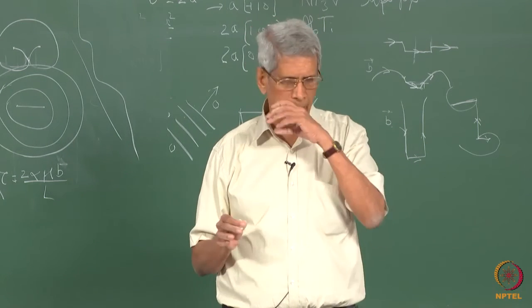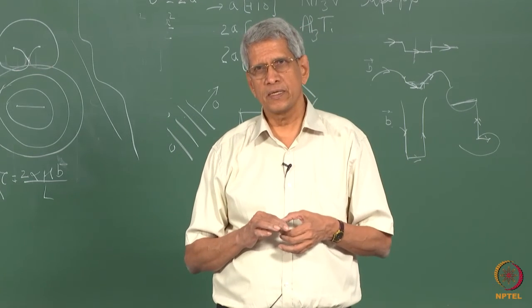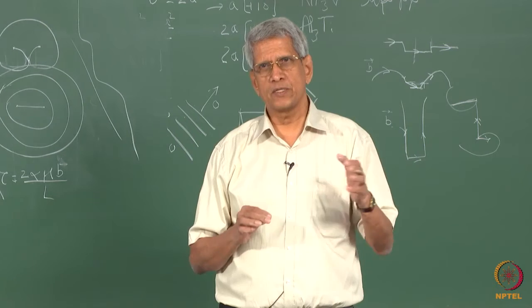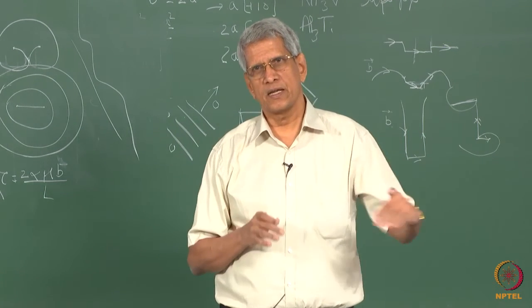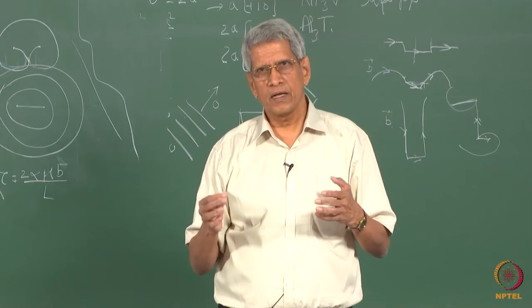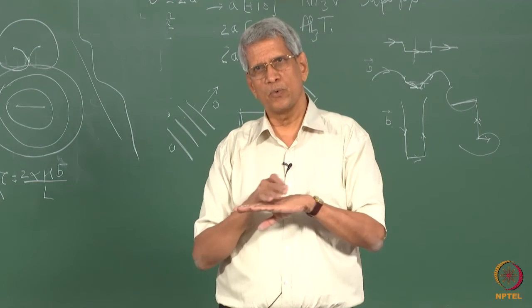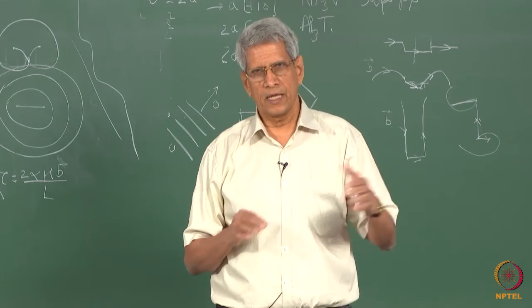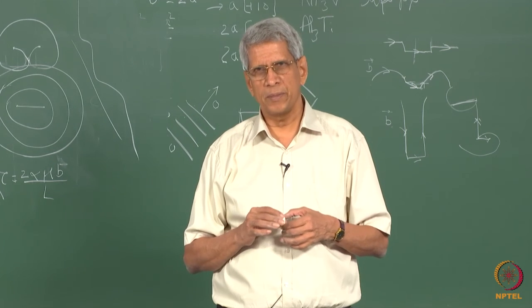When the applied stress is low and only one slip system is activated, or when the stacking fault energy is low, the dislocations are confined to move in only one particular slip plane, and then a planar arrangement of dislocations will occur in the material.